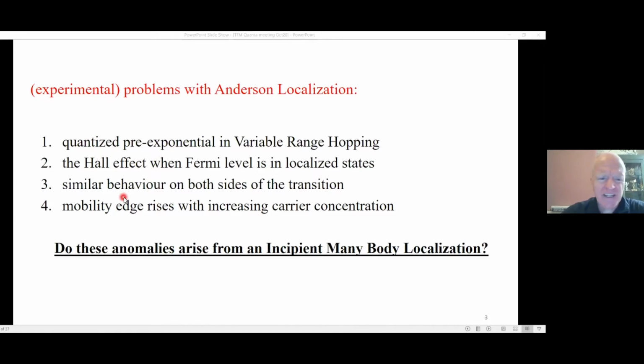And also, intriguingly enough, if we are in a region of activated conductivity, the mobility, which is also thermally activated, that activation energy seemed to depend on where the Fermi energy was in the band. So the mobility edge was moving in the band as a function of carrier density. Very strange. So the question was, do these anomalies arise from perhaps a more fundamental mechanism which is going on in the system, perhaps an incipient many body localization?